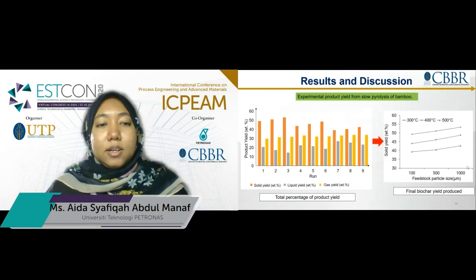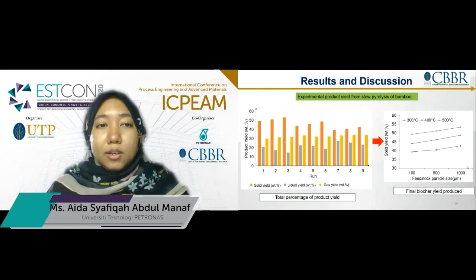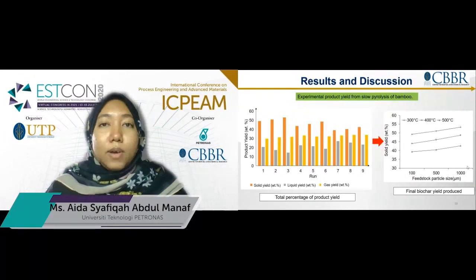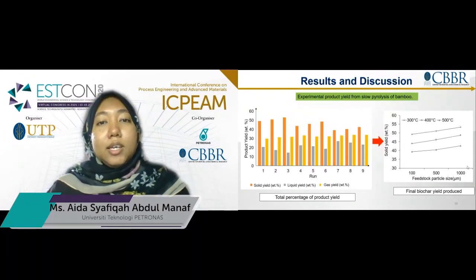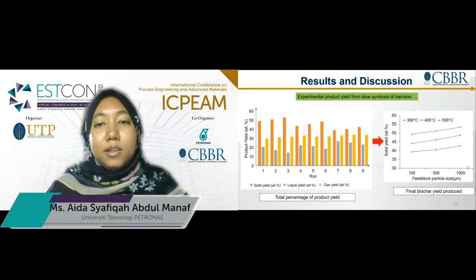As you can see, these are the total percentage of product yield. We plot every yield that we found, which is gas, liquid, and also solid. But we can see that at the third run, the solid yield is the highest compared to others. Meanwhile, at the 7th run, we can see that the liquid and also gas yield are the maximum compared to the others. But in terms of our experiment, we want to see the biochar yield instead of that yield.